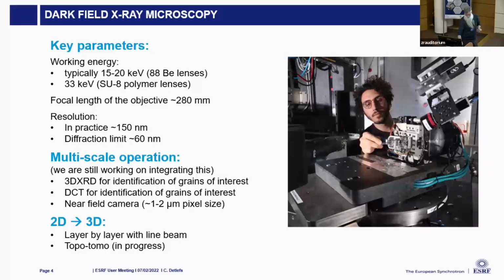And we want to integrate that, especially with 3D XRD and diffraction contrast tomography. And we already can do 3D studies by focusing the beam onto a line and then doing section topography, illuminating one layer at a time of the sample, and then in software stacking these layers to create a 3D volume. And therefore, not only seeing projections, but really seeing 3D images.